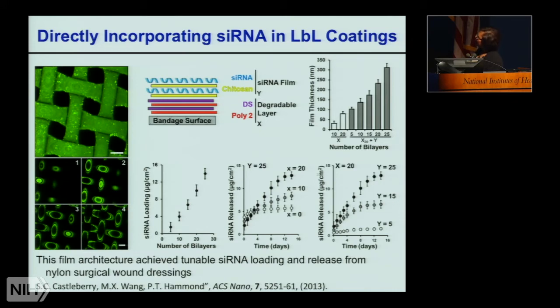We directly incorporated siRNA into these films and layered them onto a nylon Tegaderm bandage. Here, siRNA is labeled with this fluorescent marker, so you can actually see it in confocal. We're showing that we're coating all of the crevices. We changed the relative number of layers of the underlayer to change the release rate, and the top layers to change the loading.